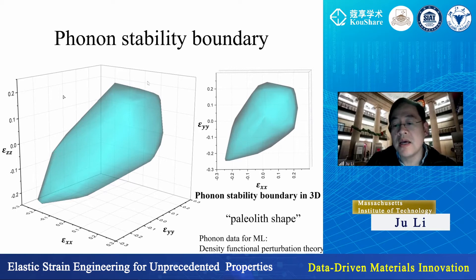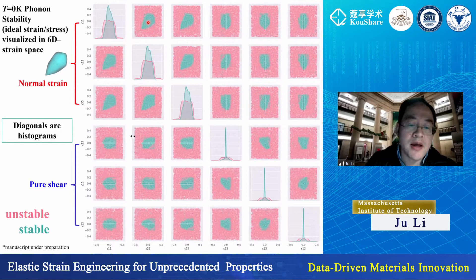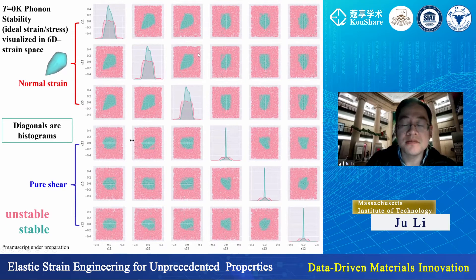It's very rich: you can take diamond from indirect band gap to a direct band gap material, then to a direct metal — even in diamond without graphitization, still in sp³ hybridization. For the first time, we can visualize the whole ideal strain surface, which is a five-dimensional object in six-dimensional strain space with singular piecewise-continuous features. The cyan color means stable — all phonons have stable real frequencies; pink means one phonon has lost stability. These are the three normal strains and three shear strains, and we obtain a mathematical descriptor of what this ideal strain surface looks like.